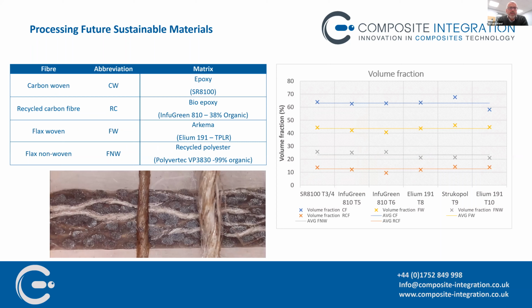On the resin side, the bioepoxies have come to prominence recently, and the material we looked at was a 38% organic content epoxy system. Arkema Elium is a thermoplastic liquid resin system which has slightly interesting chemistry in that it acts like a thermoset but can actually be recycled like a thermoplastic. And then recycled polyesters, which are actually 99% organic, according to the data sheets.